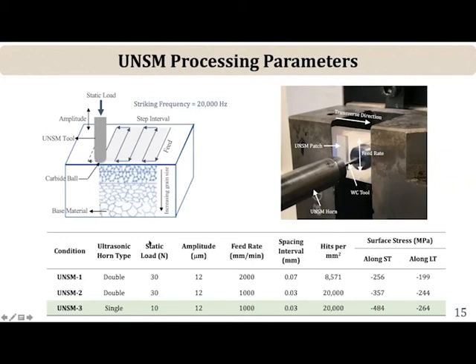One is the static load. This is a constant load over and above the dynamic load. The amplitude in terms of how much you're moving the tungsten carbide tool, the feed rate, the rate at which you move the tool, the spacing interval between the hits. And this gives you some idea about how many hits there are per square millimeter. And then the surface stress measurements are shown here.